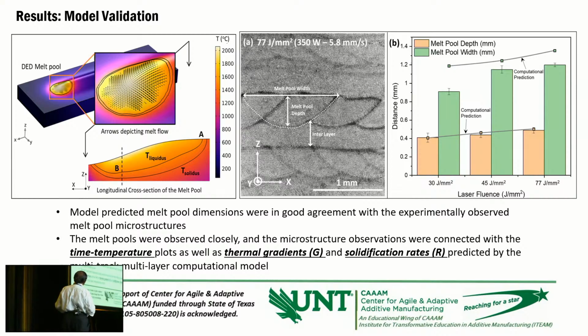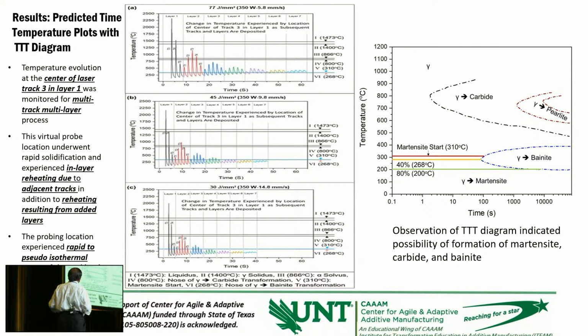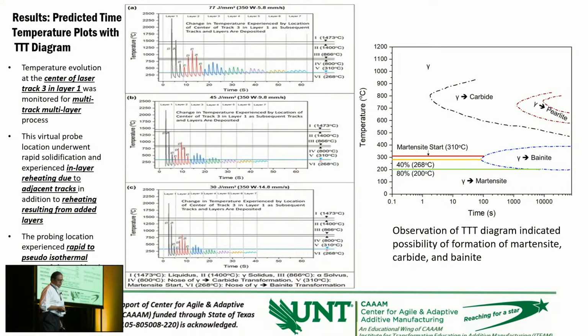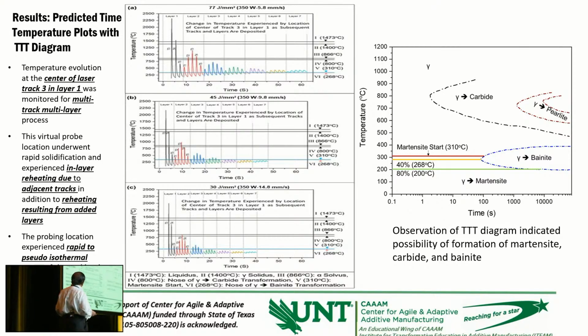So with this, what we do is we predict the phase transformation in the material, or the time temperature transformation in the material. You can see these are three different conditions. As I mentioned earlier, the H13 deposition or the AM process was done under three different input energies, 30, 45, and 77. These are the temperature cycles, and you can see the highest temperature and various important temperatures given here, and these are the temperatures of the various transformations in the material, H13: melting point, then transformation of austenite to martensite, and so on. Those can be easily predicted. And how often that temperature is raised at that point is given by these thermal cycles. These are the thermal cycles at the same point, layer by layer.